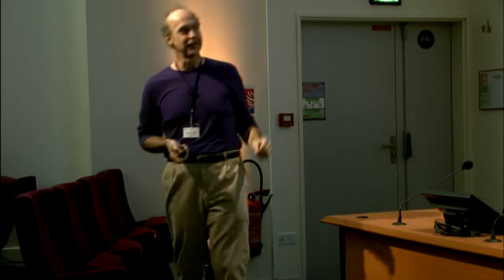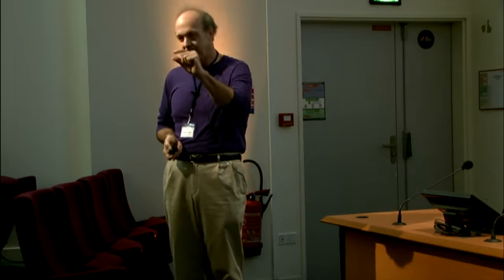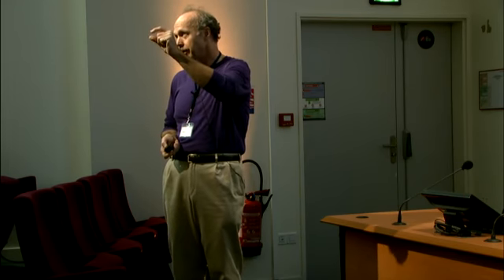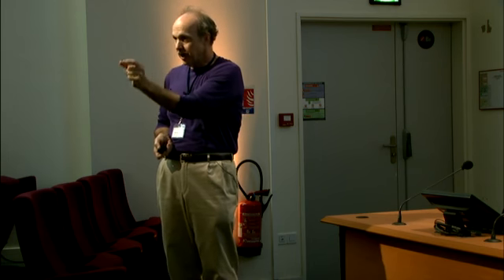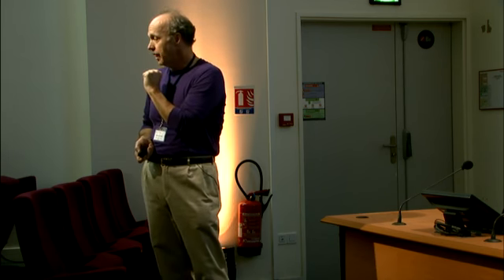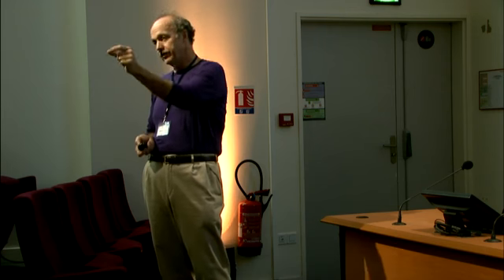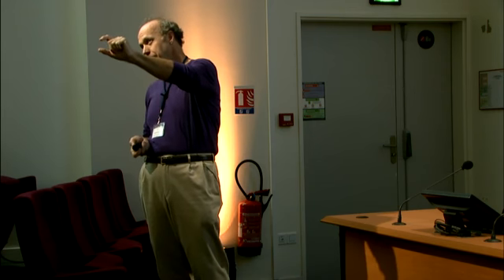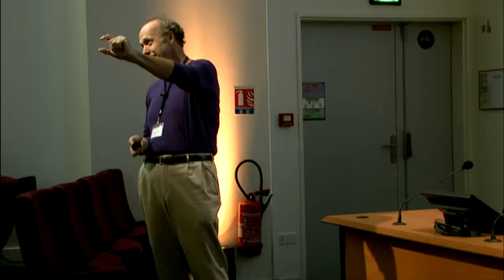This is only a 47 atom difference in average particle size, and yet it looks like we're now making peroxide rather than water. And if you're a water oxygen reduction person, you can imagine that there's just not enough space on these really little particles for dioxygen to have its dioxygen double bond parallel to the surface, and then it might bind end on and make peroxide instead of water.